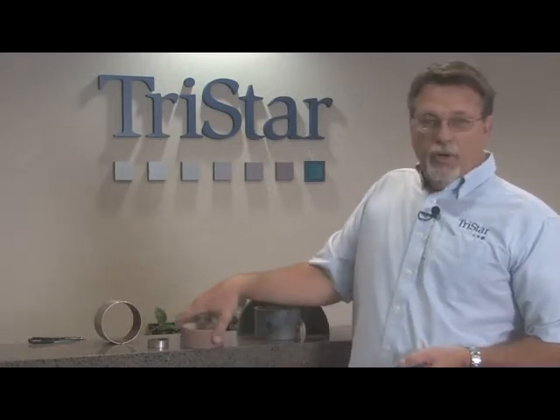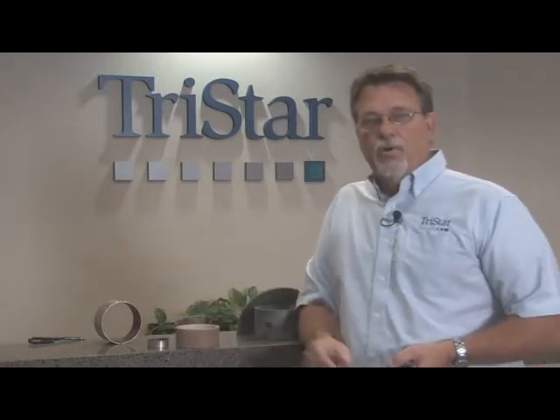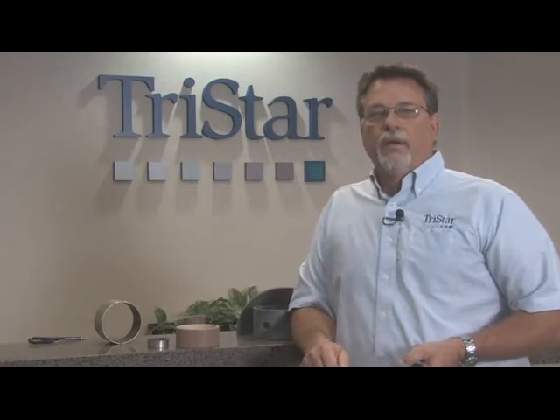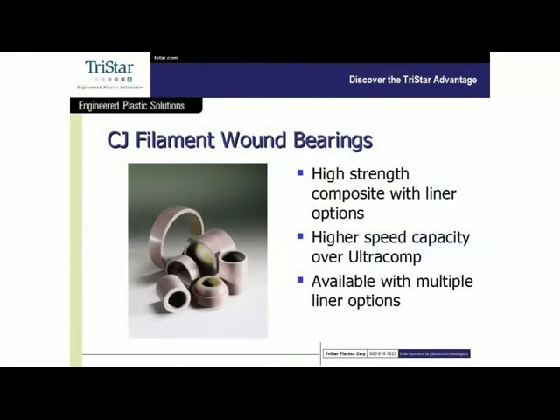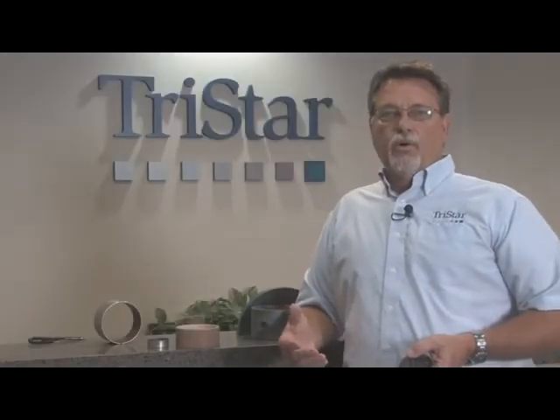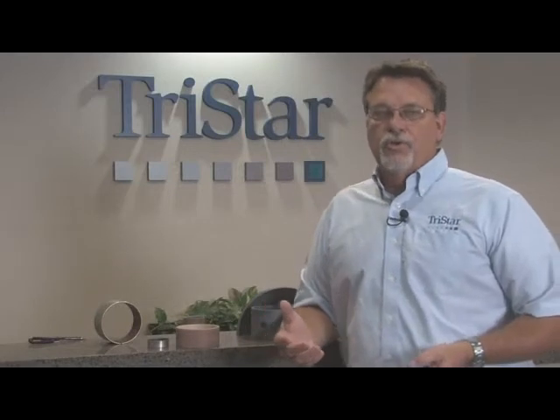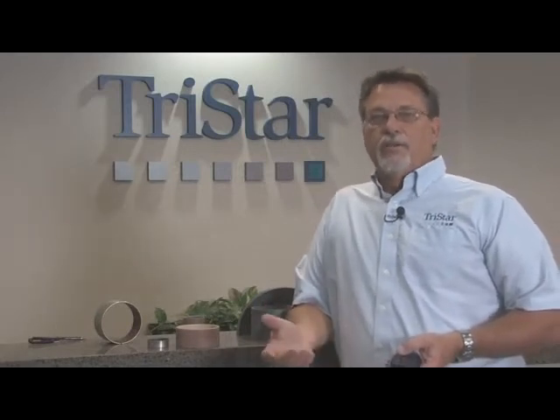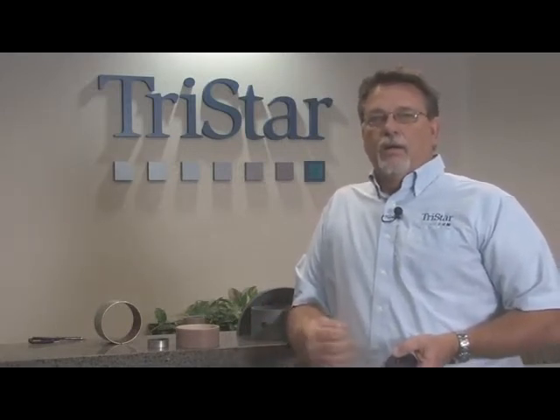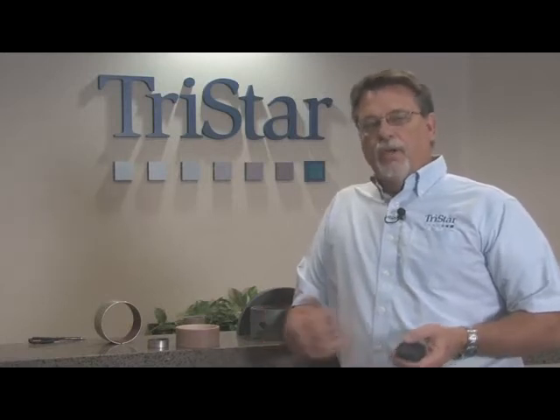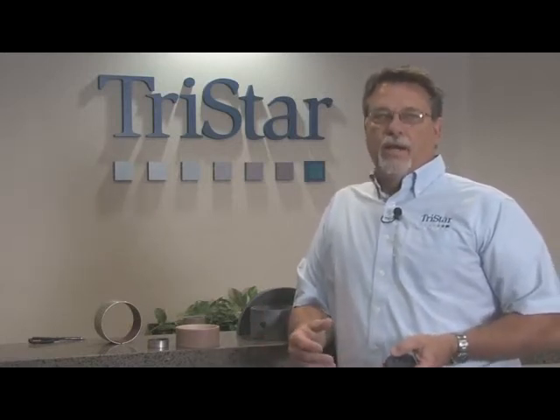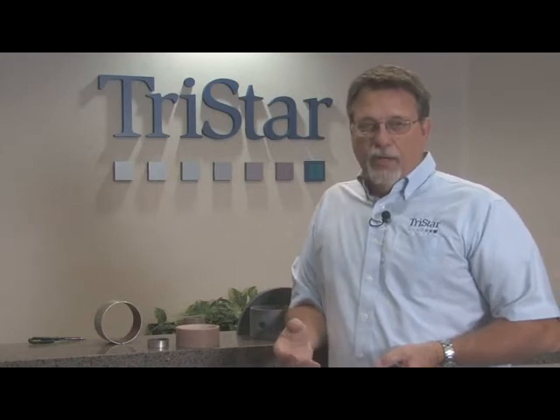Now with the CJ product line, it is also considered to be a very high load material. Design numbers are 35,000 psi on the CJ, a little bit lower on the lined versions of the CJ, but in reality these materials can go in room temperature conditions at static loads as high as 60,000 psi. But again, for design purposes, we're looking at 35,000 psi as our compressive strength.